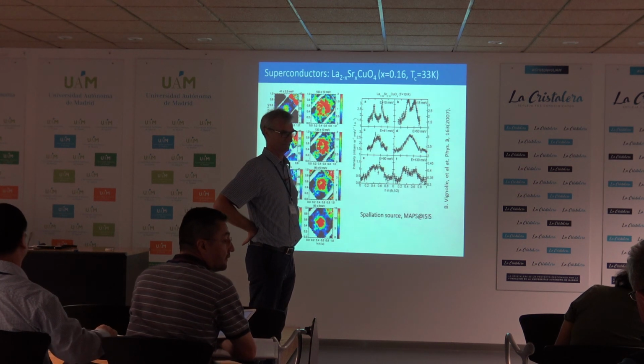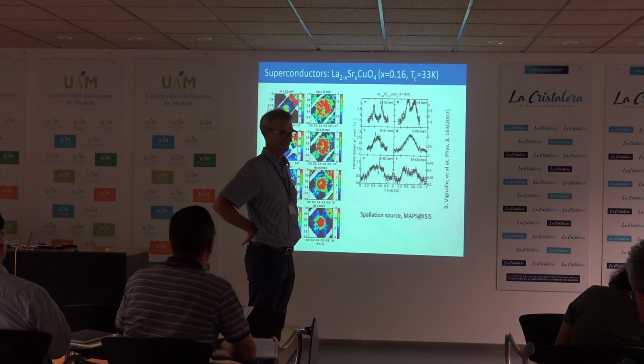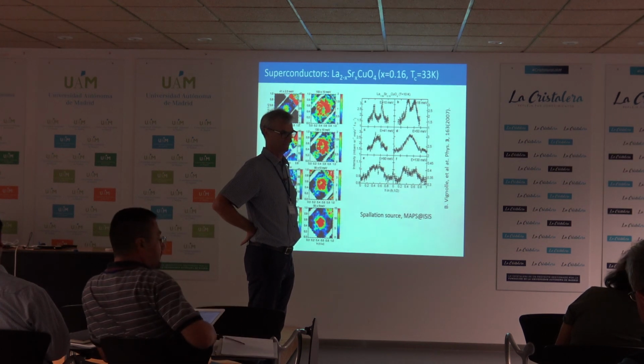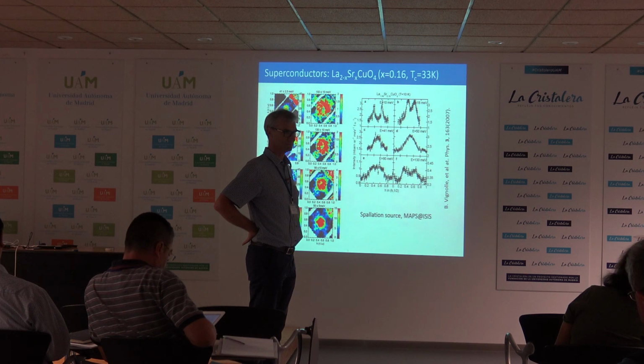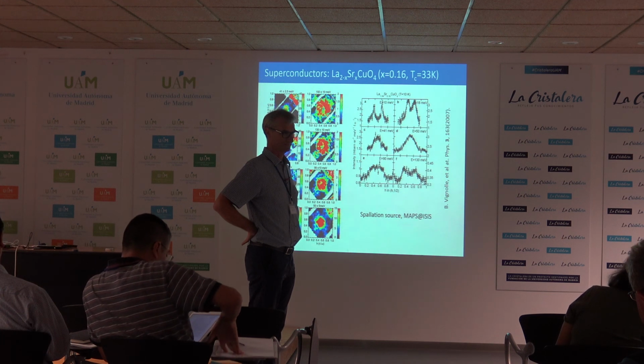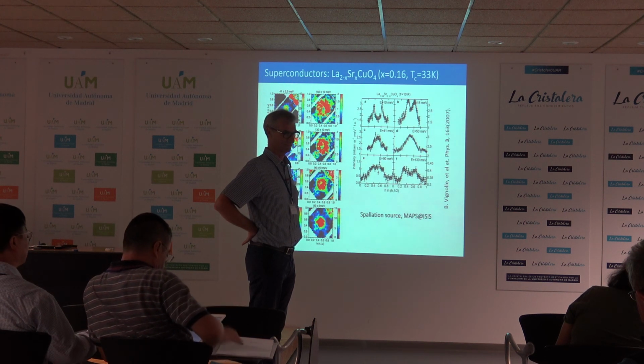And then also the imaginary part enters. At lowest frequency, it exactly determines this peak there. As I go higher in frequency, peaks get much broader in momentum space because of damping in frequency space. But still, if that damped oscillator picture is right, the real part should have a peak of the sharpness of the low frequency part.